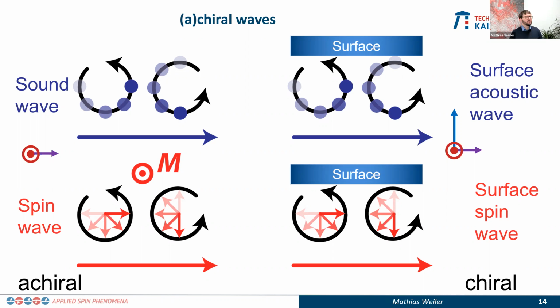I think the big problem with the bulk acoustic waves might be to really get this chirality, right? To really get this elliptical lattice motion. Because as far as I'm aware, the easily available modes are the pure compressional waves or the pure shear waves, right? That don't allow for these fancy physics. I would not give up surface acoustic waves quite yet. And that is mainly due to nonlinear interactions of phonons themselves. So we can, in the lab, quite easily achieve frequencies above 20 gigahertz of these surface acoustic waves. Okay, thank you very much. Still be helpful. Yeah, thank you.